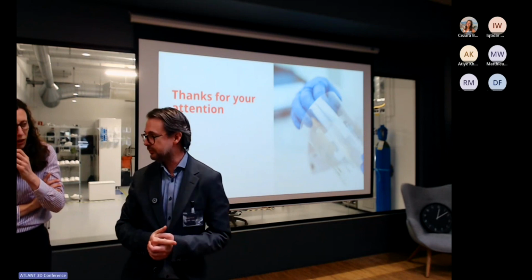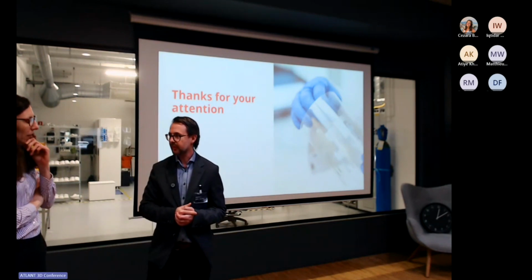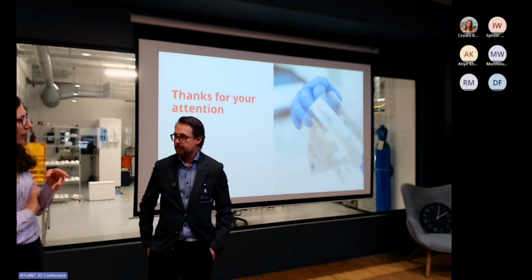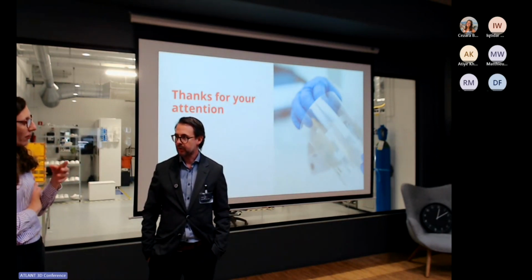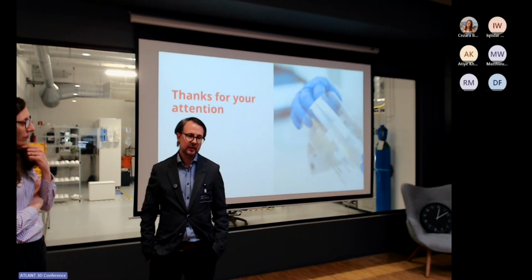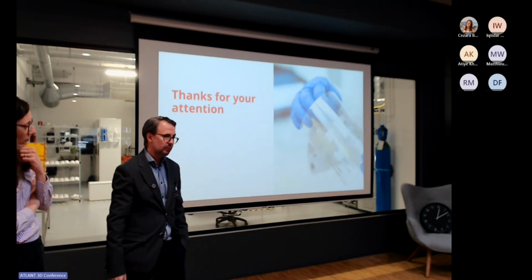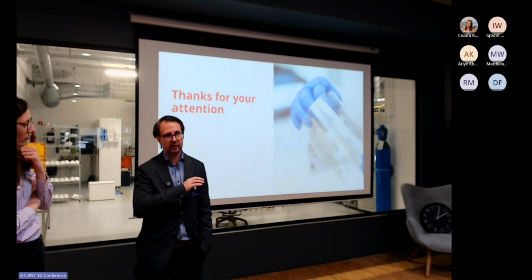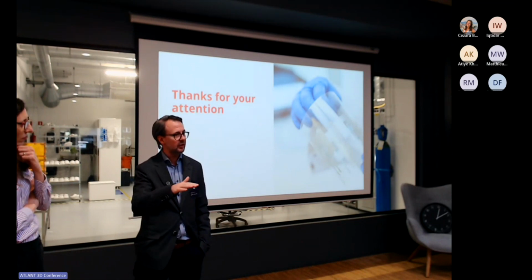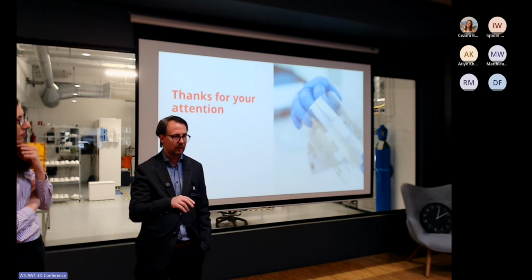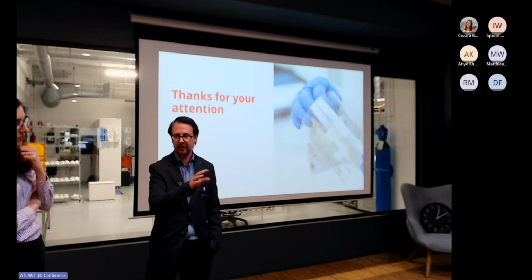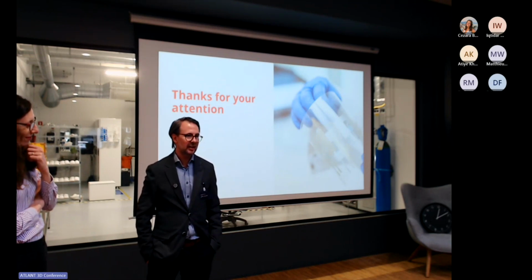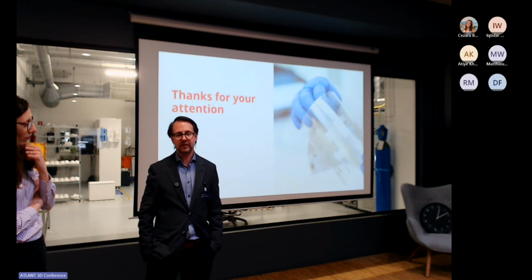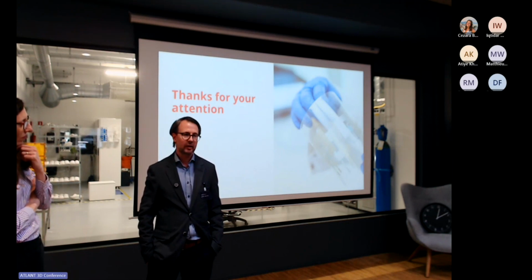I have a question. Have you seen limitations in terms of thickness and how it can prevent flexibility? Yeah, in this case, you saw we're using screen printing. Screen printing is a technique where you have, per layer, around 10, 15 micrometers. So it's called thick film compared to ALD. And actually what we see is the thicker the better in this case, usually. When you get to these thin layers, then the stretchability becomes very difficult.